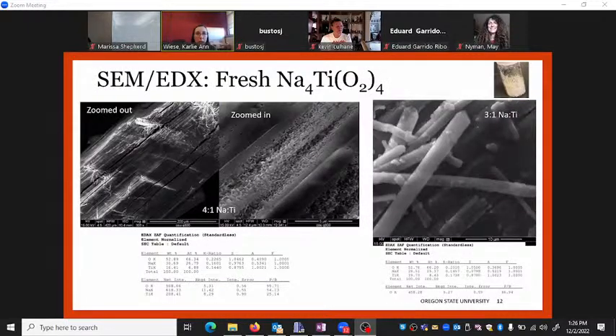So here are some images I took from SEM and our EDX results on the sodium tetraperoxytitanate structure. The first images here are the same crystal zoomed out and zoomed in. And the EDX shows us that the ratio is 4:1 sodium to titanium, which is exactly what we got for our formula from the single crystal data. So that further confirms that.